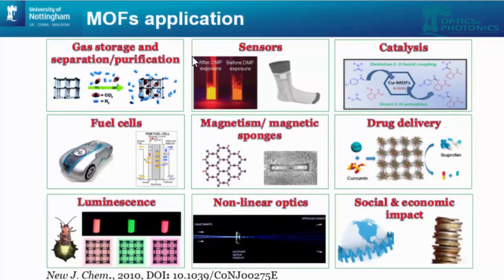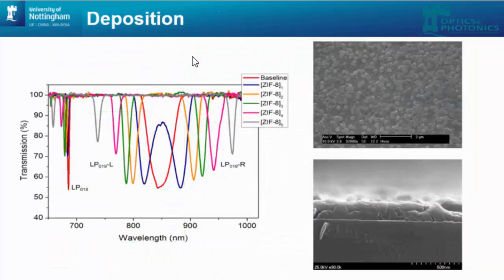The main application of these materials is in gas separation. Because of this high porosity, they are very good at storing different gases. You can tailor the selectivity of these materials by simply changing the metal node or organic ligand, so you can have different materials. This provides a prospect for sensor development. So we have combined these two. We combined long period gratings, optical fibers, with metal organic frameworks, and I'll just show you the deposition results here. It was very simple.